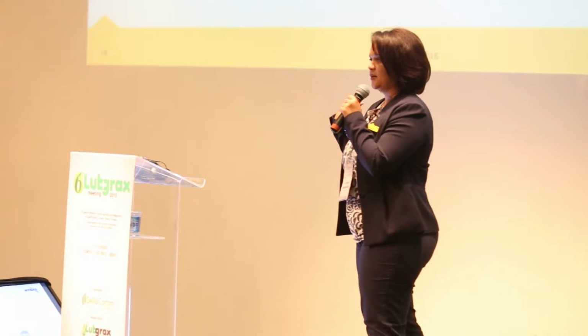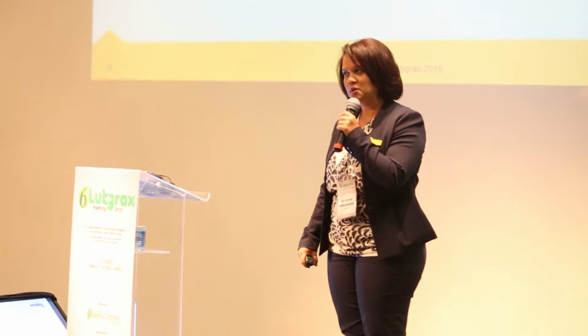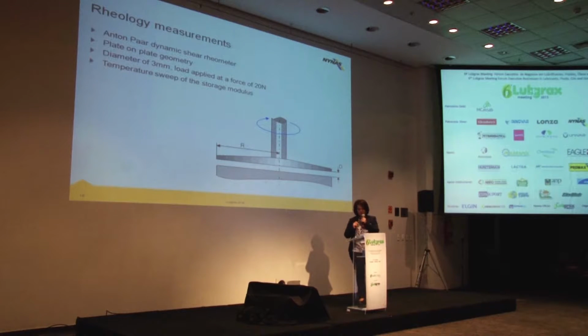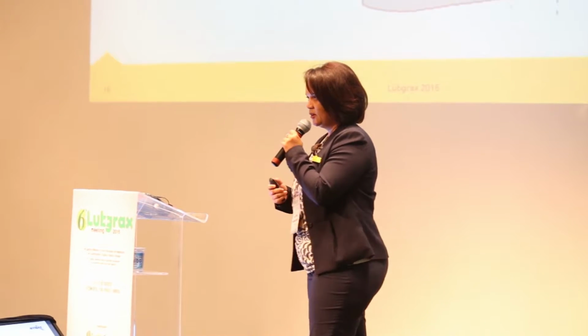So in order to verify those flow pressure results, we decided to look at rheological measurements. I'm sure you're familiar with the Anton Paar dynamic shear rheometer. For this particular experiment, we used a plate-on-plate geometry. We have the option of using cone on plate and several other geometries. The diameter is 3 millimeters, and then a force applied on top of 20 newtons, and then the sample is sheared, meaning that the top plate starts spinning, and then you measure the response to the force applied. And then I ran a temperature sweep.